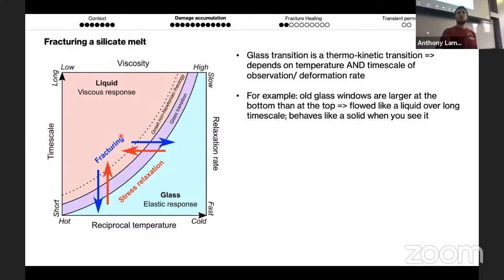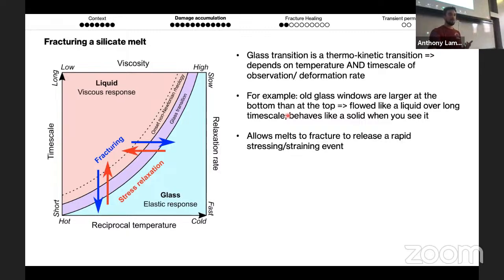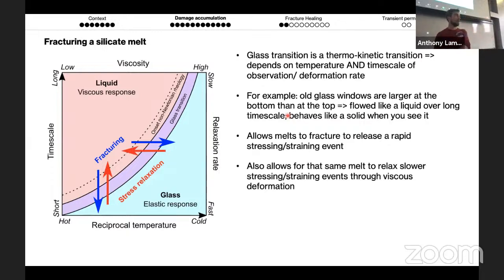A good example of the glass transition is in churches. The really old glass windows will be thicker at the bottom and thinner at the top. If you throw a rock at one of those, well, probably don't do it on the church, you're going to break the glass, so fast strain rate. But over a long time scale, that glass, even if it appears solid to us, still behaves as a liquid. That's an example of that. What that means for volcanoes is that the melt being able to fracture is a good way to release a rapid stressing event, but healing also means that you can recover coherence in the material if you leave it for long enough.